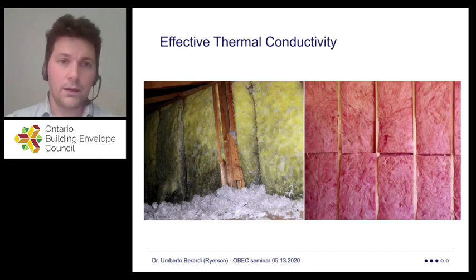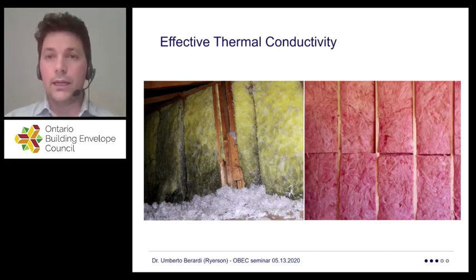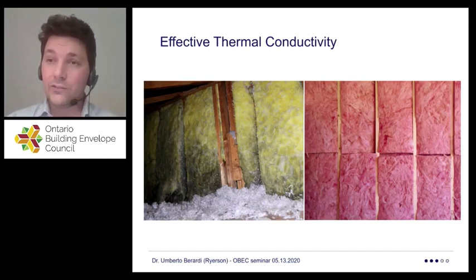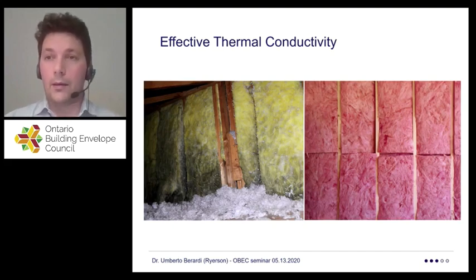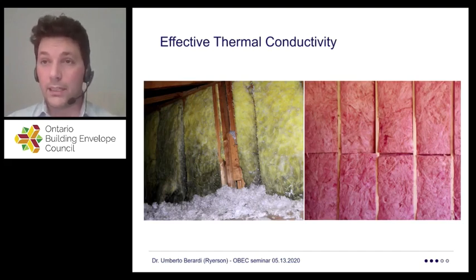And in both cases here, a main concern is the fact that we get a lot of moisture and a lot of condensation. So in the field, the reality is that material is not as dry as companies bring to labs. When I receive materials in our lab to be tested, they are as warm as a new pizza, coming out from an oven, and there isn't any actual humidity. But in reality, a lot of our enclosures tend to have a lot of fluctuation in relative humidity. So moisture content gets trapped in the cavity.